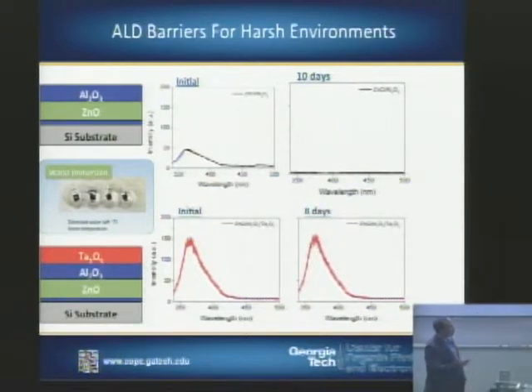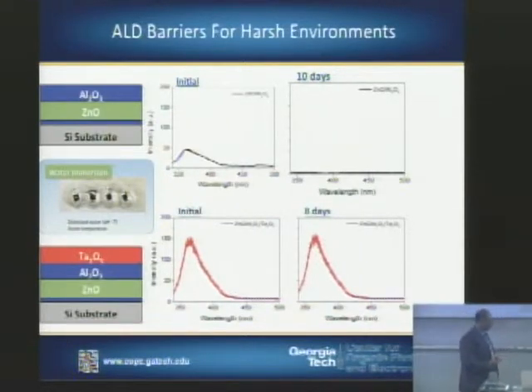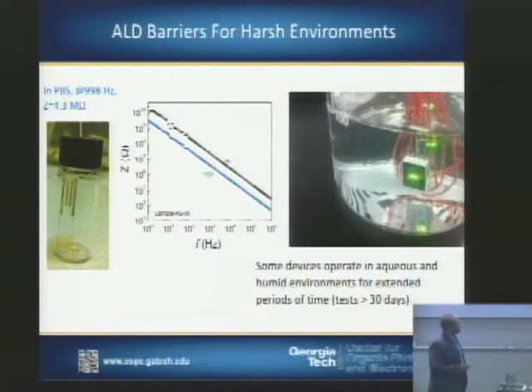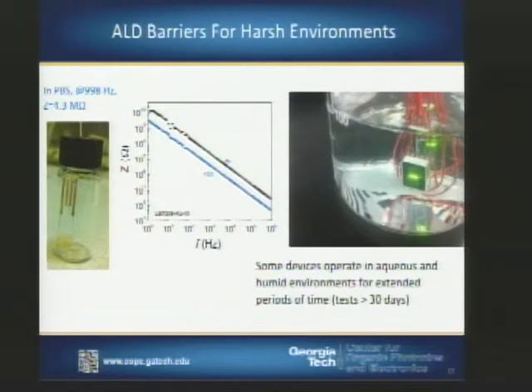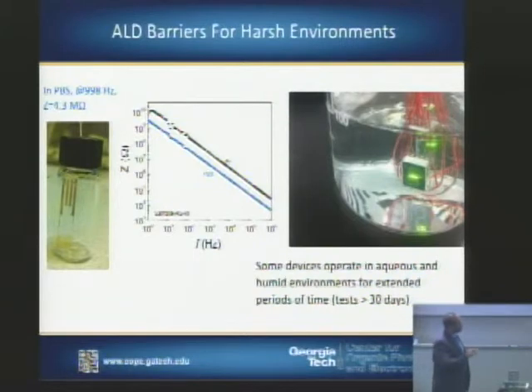And so we're using zinc oxide that's coated with a layer of aluminum oxide, which is a common barrier film. If you leave this in water over a period of days, you will notice that the zinc oxide, which is detected by photoluminescence, the peak from the zinc oxide will disappear. But there are a number of other oxides you can add to this where it gives you very nice stability. So we're looking at combinations of materials that will allow us to have survivability in these harsh environments. More recently as well, we've looked at some electronic devices, and again, this is a different combination of ALD layers that we put on top of our electronics.